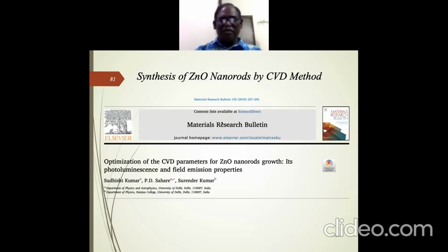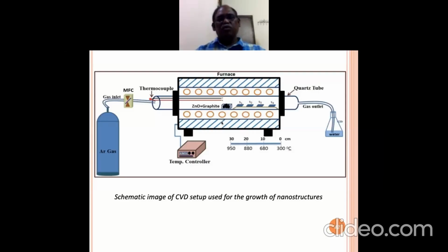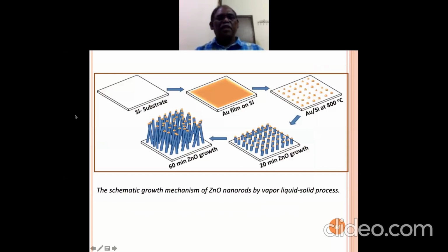So then we have also synthesized this by CVD method. This CVD facility we have developed in our laboratory, and this is the setup. Here we have taken a silicon substrate. We have coated it with a thin gold film, and at a certain temperature, when it melts, it forms some droplets. So it is very, very important to monitor the temperature. The important thing about this kind of technique is that these droplets act as seeds for the nanorods, and that is how the nanorods are formed. Or you can form these seeds and also grow on those seeds by another technique also. So that is the beauty of it.